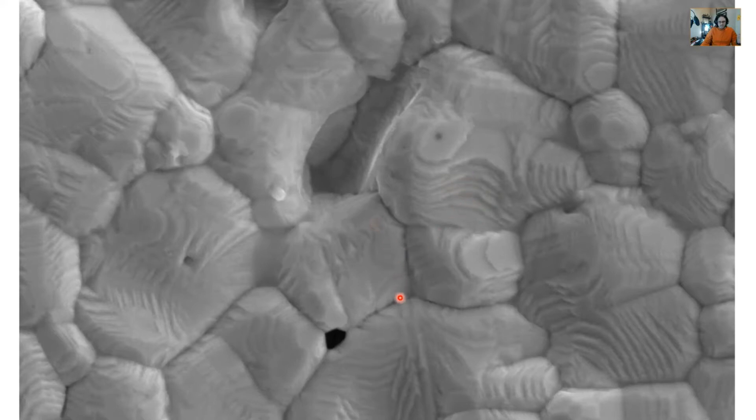And we also see a lot of grain boundaries. There are some triple points here. So that's really cool, grain boundary triple points. And they're almost in the classical depiction of a grain boundary where you see this honeycomb structure start to form, because that's the lowest surface energy configuration that grains can really achieve. We see some pores here, so I can tell you that it wasn't pressure assisted sintering, because we have some pores, we have some empty voids.